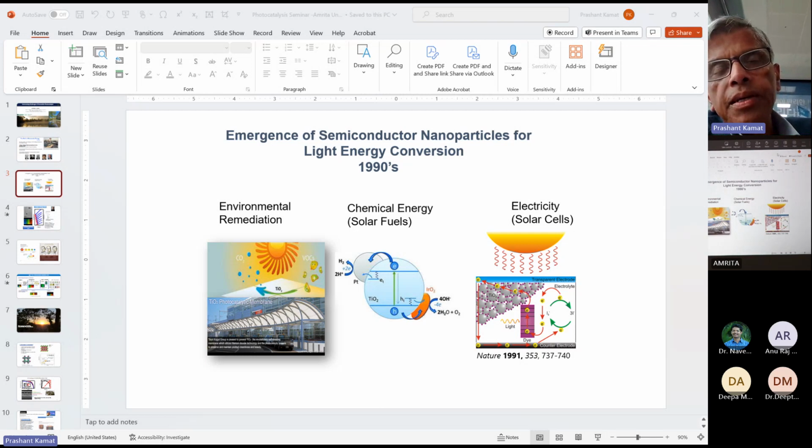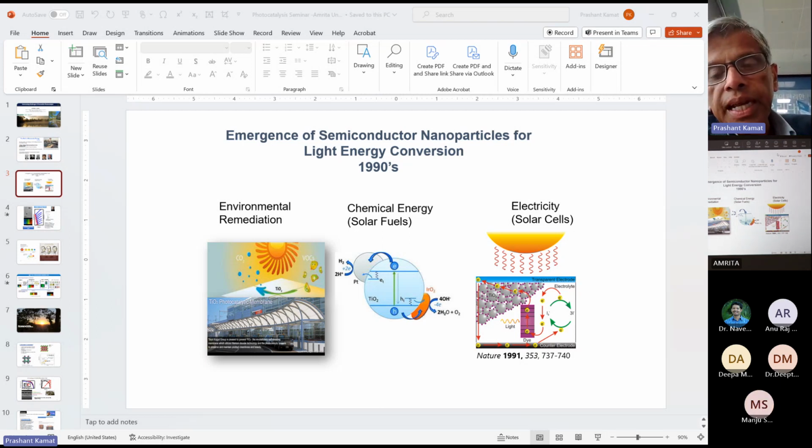Typically, all nanoparticles have certain charge. Mostly they are negative charge. It's built in, either with the solvent or with the ligand. So what you do is you put two electrodes in an electric field, and the solvent needs to be non-polar. The reason is that when you pass this high voltage, anywhere from 50 to 100 DC volts, it creates an electric field. And so the negatively charged particles go towards the positive electrode and get deposited.